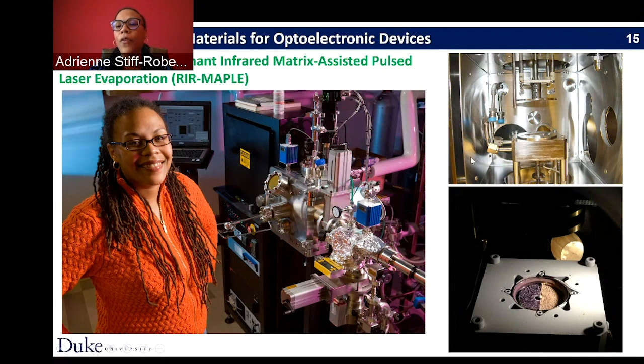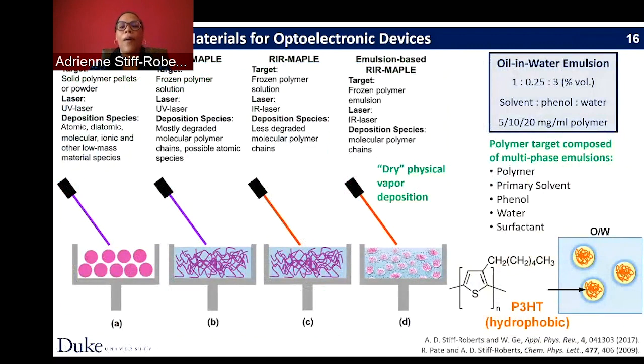So this is showing the inside of the growth chamber. There's a target cup that sits here at the bottom, and it's actively cooled by liquid nitrogen so that the target solution can be frozen, and the substrate sits above the target cup. And this is a picture of that frozen target cup. It has actually two different solutions frozen inside, or emulsion. So just to explain a little bit more about what this process is and how it works. As I said, it's a variation of pulsed laser deposition. People have tried to do pulsed laser deposition of polymers. So all of this is developed in the context of polymer thin films.